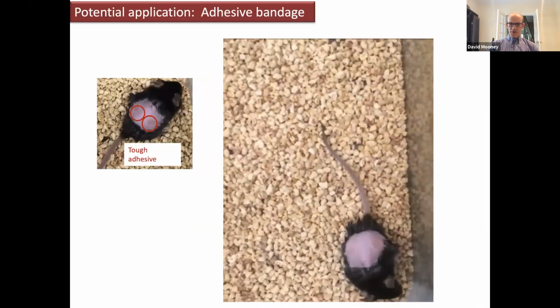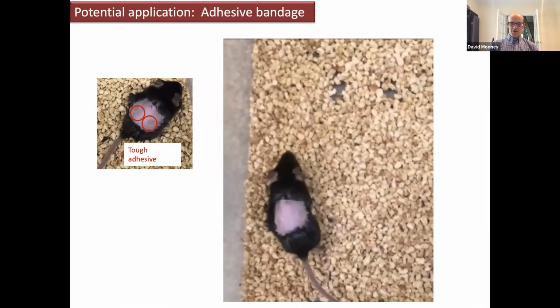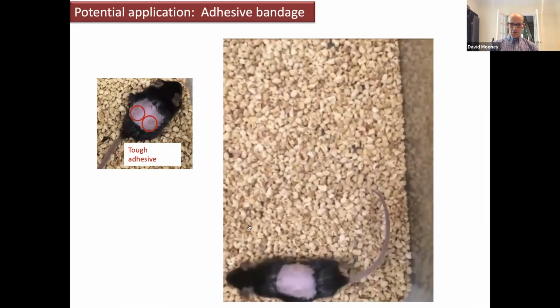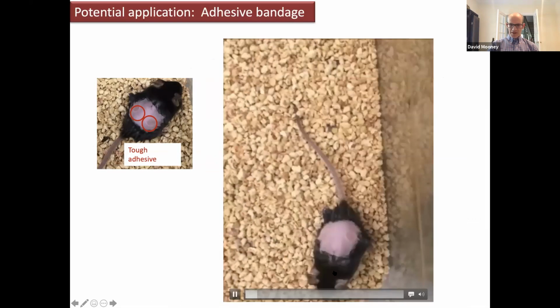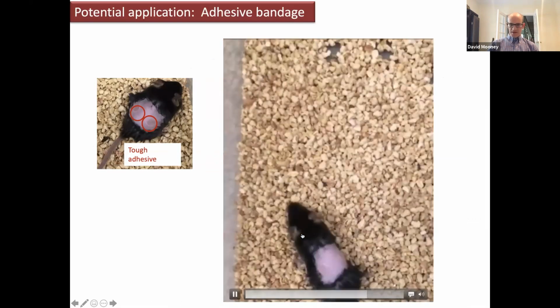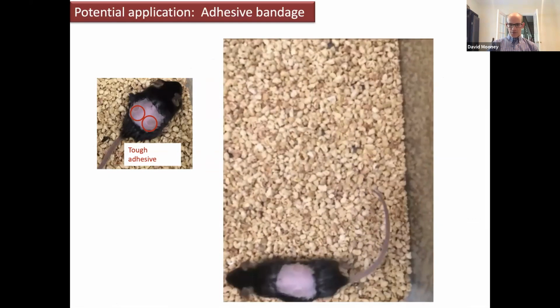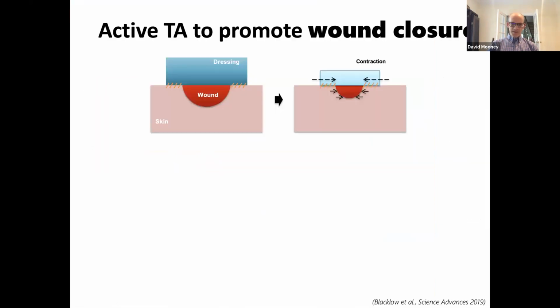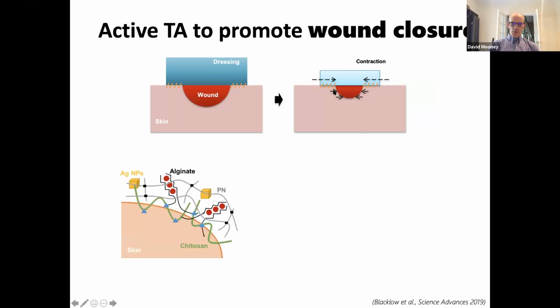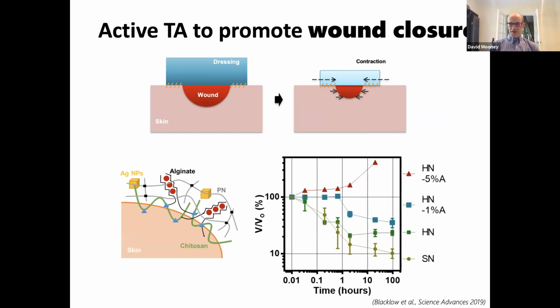Now we know that these actually adhere very nicely to the skin, as you can appreciate here from this image where we have a laboratory mouse, and two of these have been placed basically on either side. And you can see that it stays nicely adherent and will stay adherent for weeks at a time. And so what Jane Yu did to transition this from being a passive to a mechanically active system that would then contract after being placed onto a wound site was to incorporate PNIPAM that would undergo a phase transition as it went from room temperature to body temperature that would lead to a contraction force.